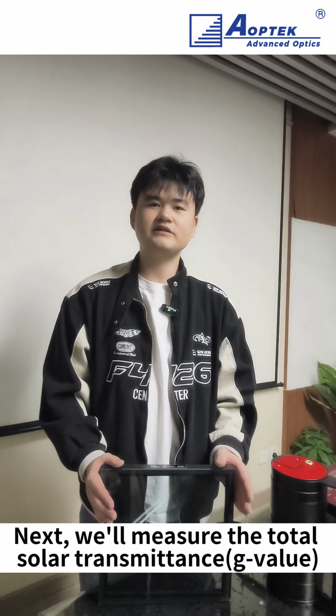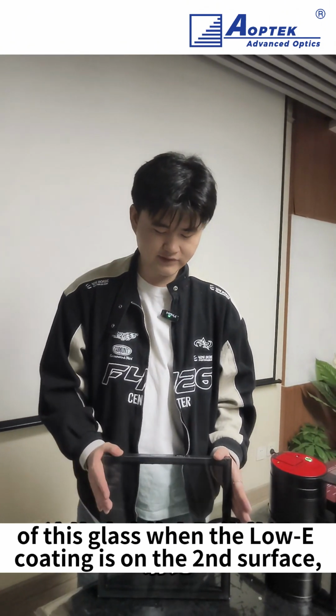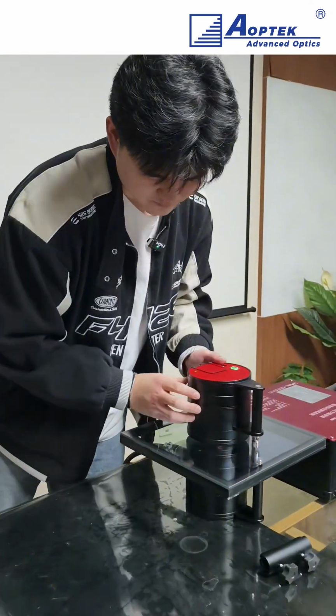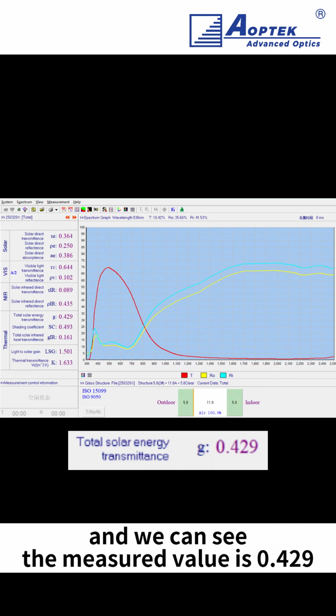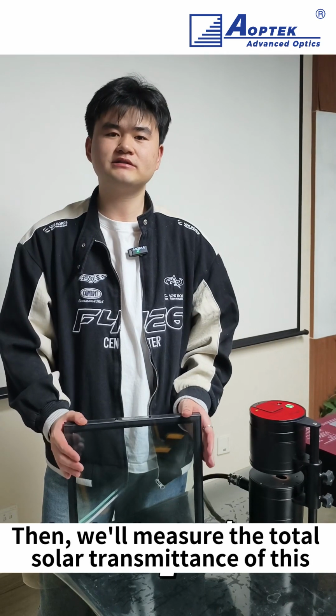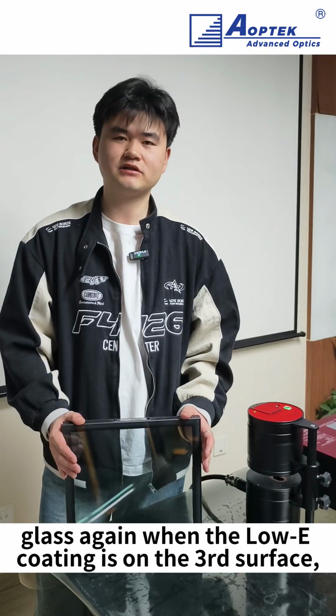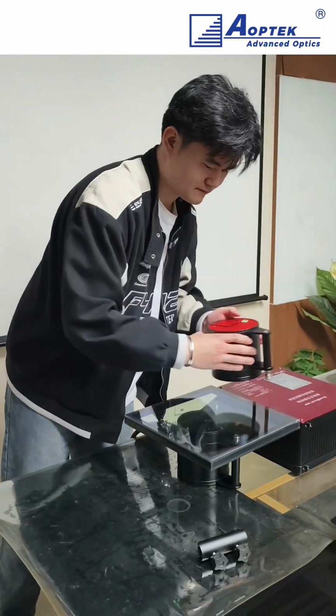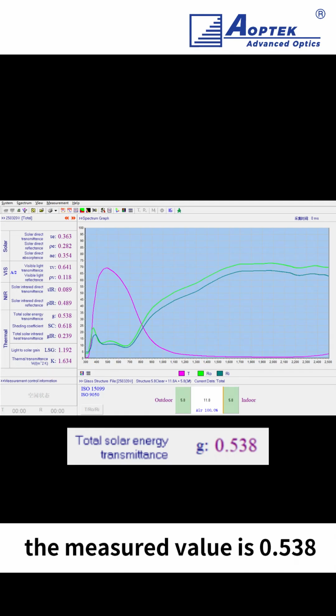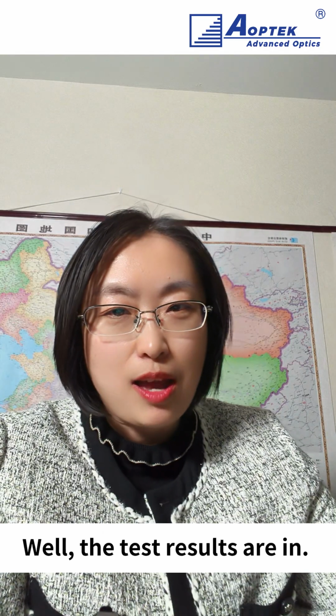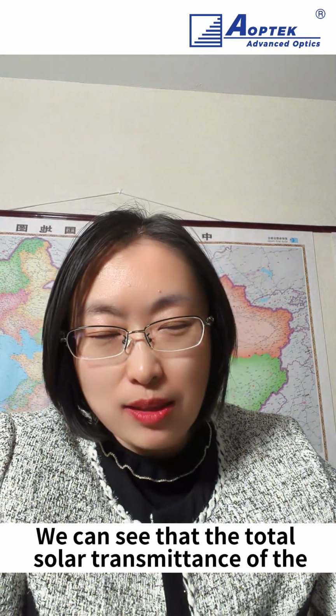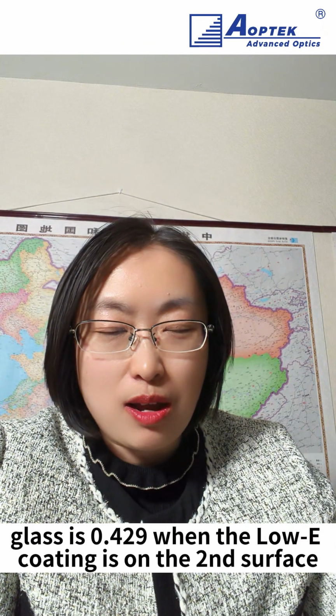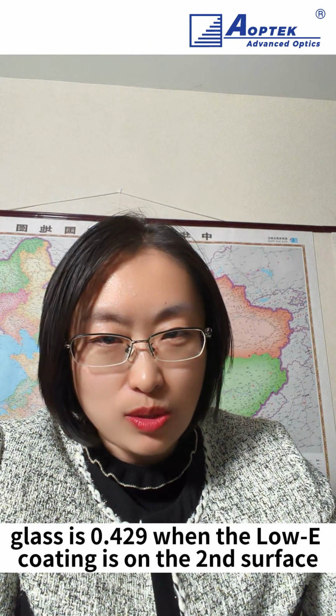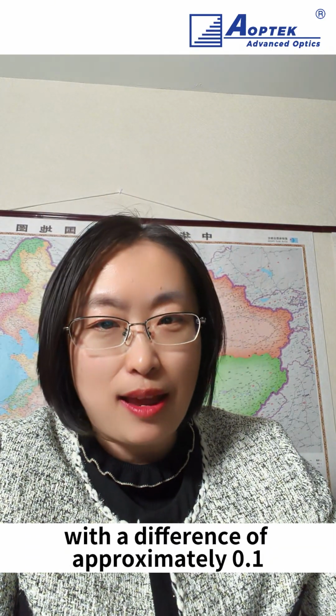Next, we'll measure the total solar transmittance G value of this glass when the Low-E coating is on the second surface. And we can see the measured value is 0.429. Then, we'll measure the total solar transmittance of this glass again when the Low-E coating is on the third surface. The measured value is 0.538. Well, the test results are in. We can see that the total solar transmittance of the glass is 0.429 when the Low-E coating is on the second surface, and 0.538 when it's on the third surface, with a difference of approximately 0.1.